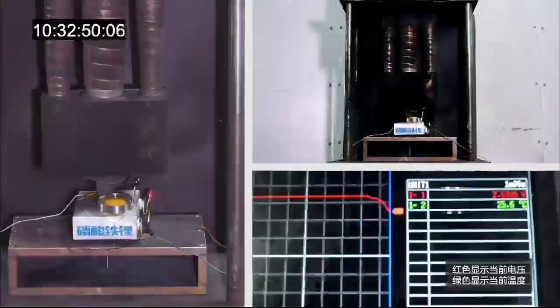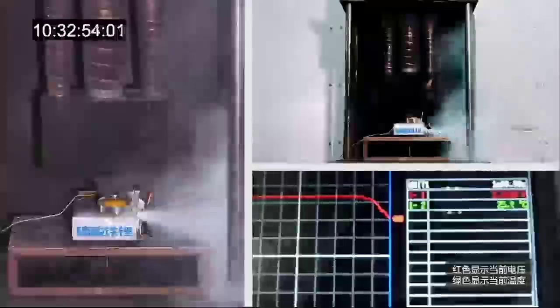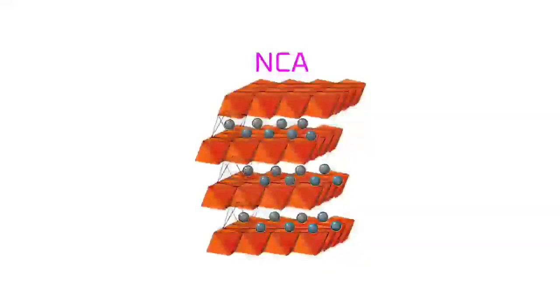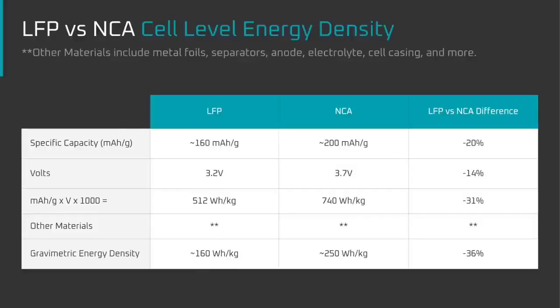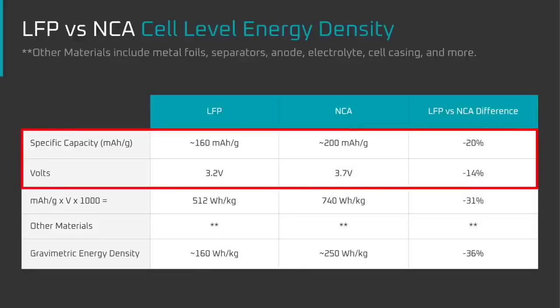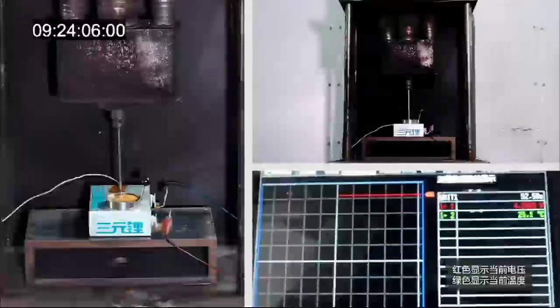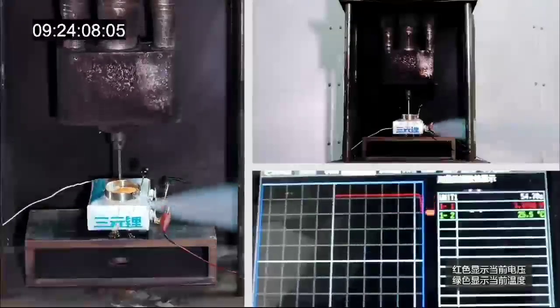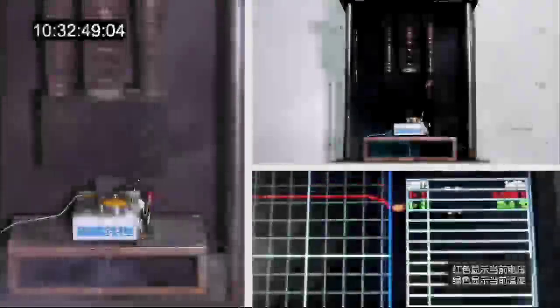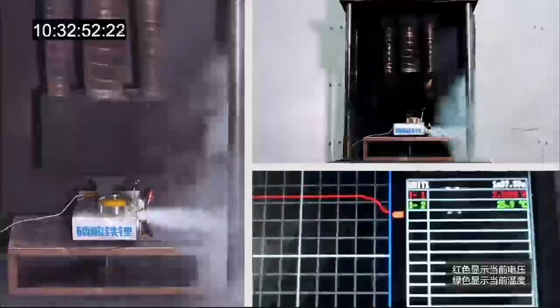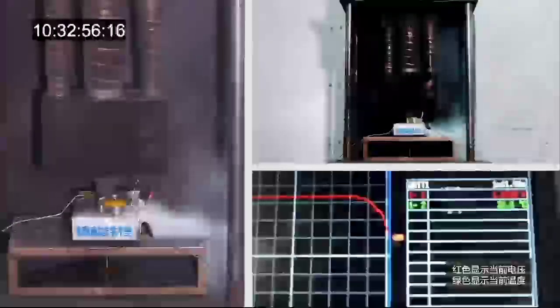This leads to a hot battery that bursts but doesn't necessarily turn into a molten fireball. Let's do a quick recap of NCA before moving on to pack level performance. NCA is higher energy density than LFP because it stores more lithium and has a higher voltage potential. The drawback of NCA is that it's less stable and results in battery cells that are susceptible to violent thermal runaway events. LFP cells, on the other hand, tend to burst and smoke. Still dangerous, but more benign.